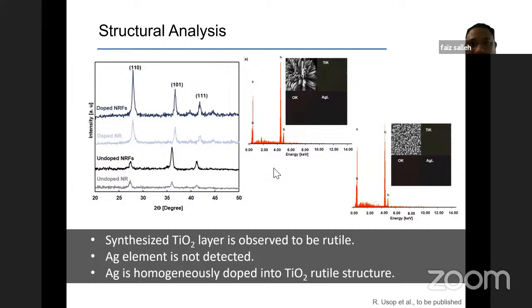Sorry for the technical issue. Okay, so if we look at the EDX result, we can see that it's quite difficult to find the peak of the silver at around 0.8 kiloelectronvolt. This is for undoped. This is for the doped. Sorry, both are for the doped at 0.4 gram. This is for the B layer, and this is for the single layer. If we look at the mapping itself, I'm sorry, the picture is not very clear, but the Ti and O we can see are uniformly distributed inside the mapping.